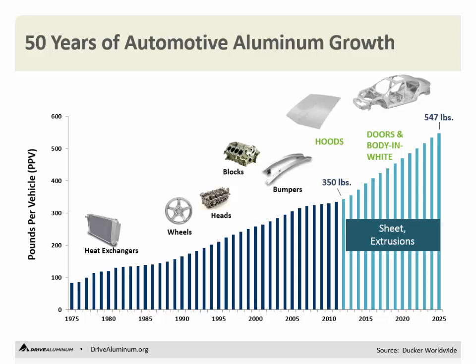The early days of aluminum, back in the 70s, were predominantly heat exchangers as the growth area. We've grown from about 75 pounds per vehicle in 1975 to 350 pounds per vehicle in 2012, and the forecast is looking at somewhere on the order of 547 pounds of aluminum per average vehicle by 2025.